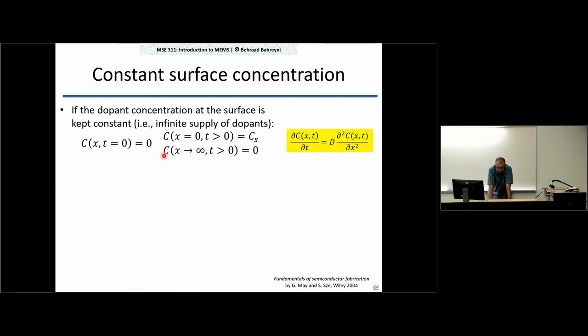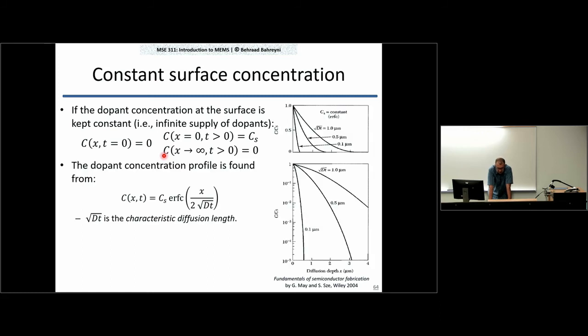If I go and solve the equation that I had, the Fick's equation that I had, I get this solution. So you can show that the concentration of dopants as a function of x and t is given by that equation. Cs is the surface concentration, what I used to keep constant at the surface by flowing, let's say, enough phosphorus or boron atoms at the surface. ERFC is the complementary error function. It's tabulated. It's a well-known function in math. And x over 2 square root Dt is basically telling you the dependence of the dopant concentration on x and t. Square root Dt is called the characteristic diffusion length, and x is the distance from the surface.